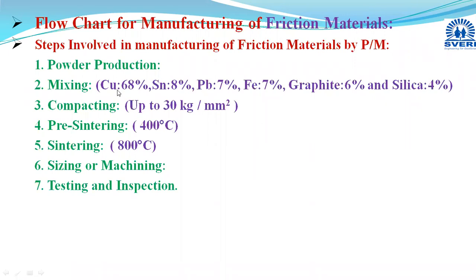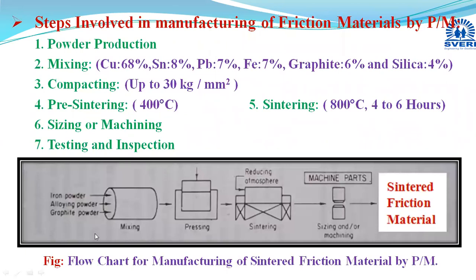And now here, as we have a number of powder particles, there will be a very high difference in their densities. To avoid their segregation, some extra lubricants or some amount of oil is added because of the high difference in their densities. That is done in the mixing stage only, and the uniform and homogeneous mixture obtained with suitable mixing or blending devices is given to the next stage, that is the compacting stage.